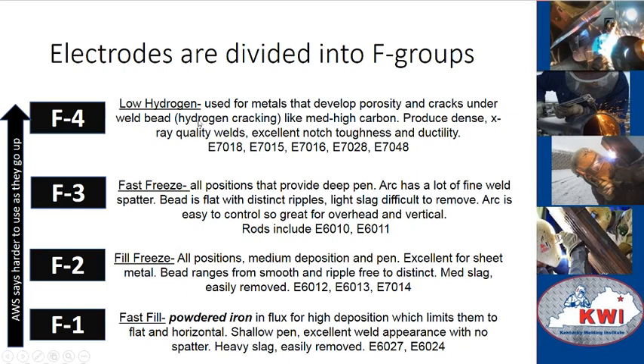So this rod is awesome. It prevents hydrogen cracking because it's low hydrogen, and it produces dense X-ray quality, excellent notch toughness, ductility. I mean, 7018 by AWS standards is the hardest one. If you qualify with the 7018 on a job, then that QC should let you weld with any of these rods below. So know for sure which is which. Your F3 rods, that's a 6010, and F4 is your 7018.